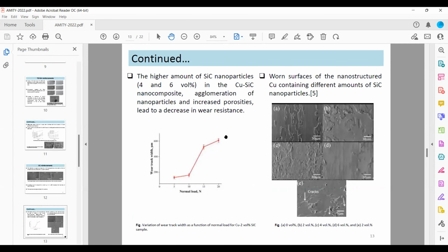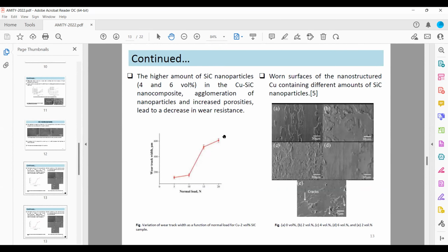Here the major wear mechanisms are considered to be flake formation and abrasion. With increasing silicon carbide volume percent, the flake percent would diminish, and also with decreasing load and increasing SiC volume, the coefficient of friction in the copper nanocomposite increases.